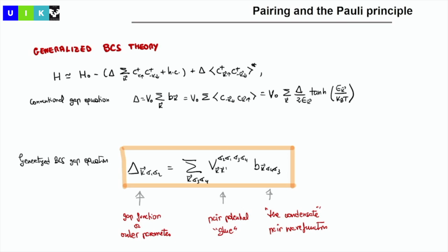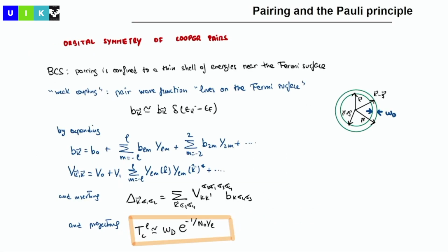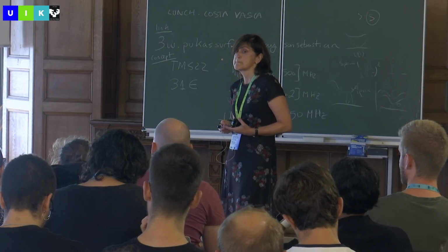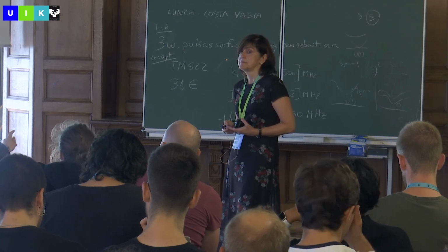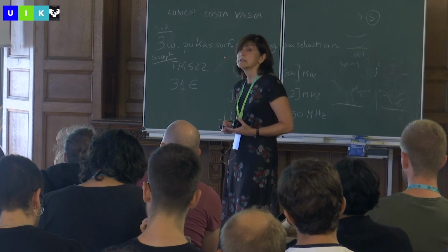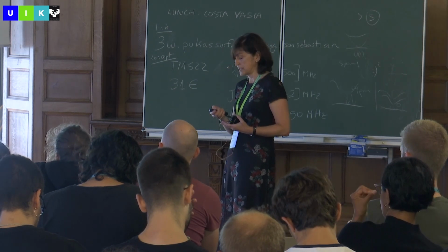Here is where you have what you are thinking about as attractive or repulsive, but this is the effective interaction between your electrons. So what you do now is you put here this interaction that I'm showing as a function of R, and you expand it. And this gives you these higher order L terms that are the dominant ones in the expression of the TC. So it comes from doing this expansion in your screened repulsive Coulomb interaction. Okay. So I guess the higher TF is, the more terms I will have in that sum over K. You go on having higher orders in your expansion. Okay, thank you. Yeah.